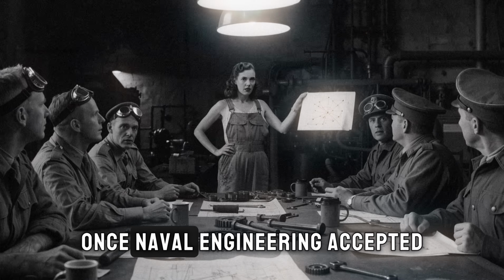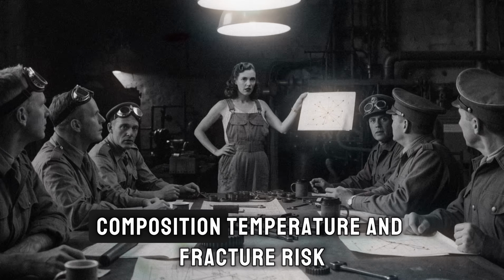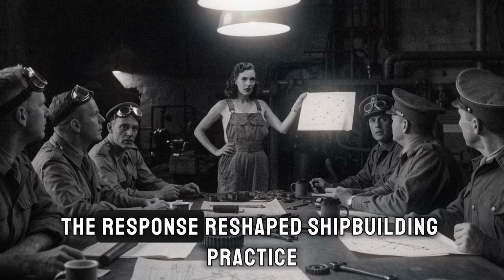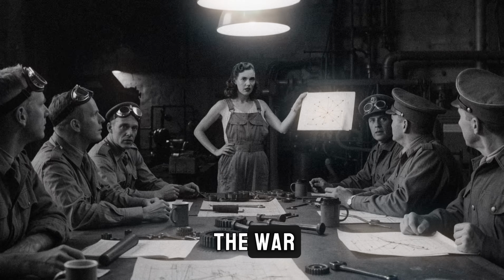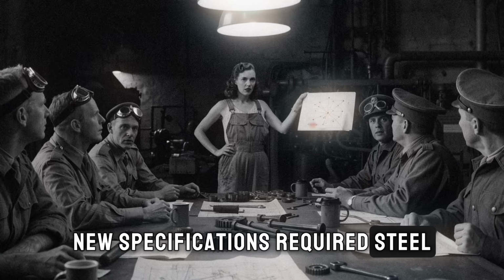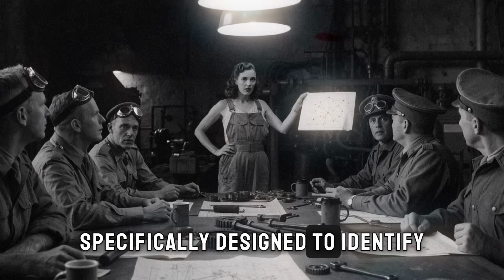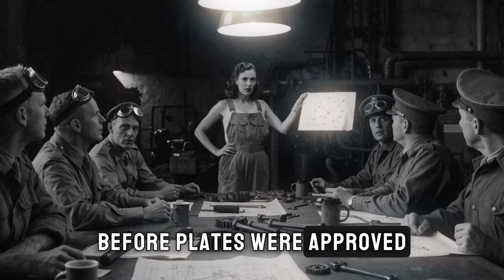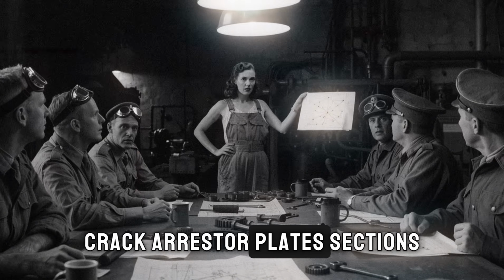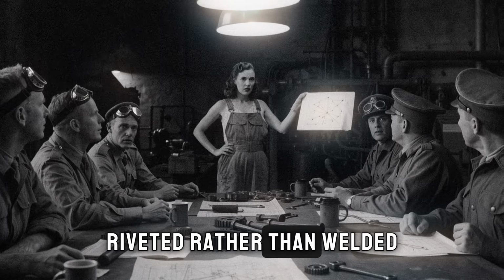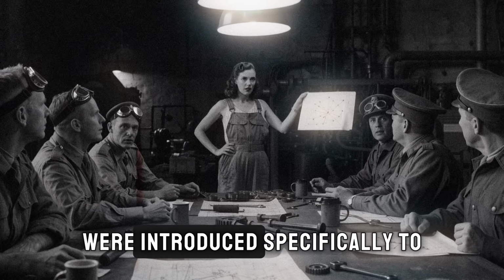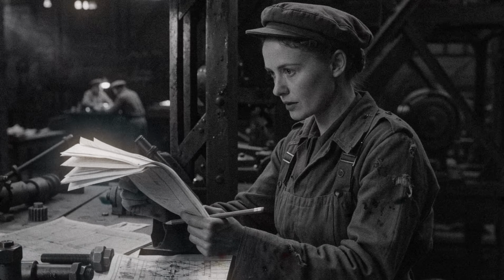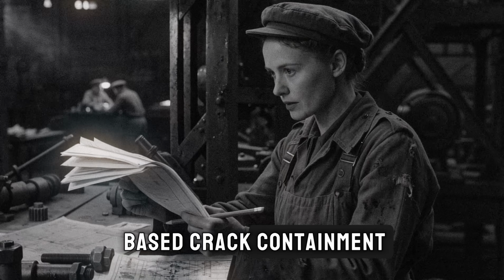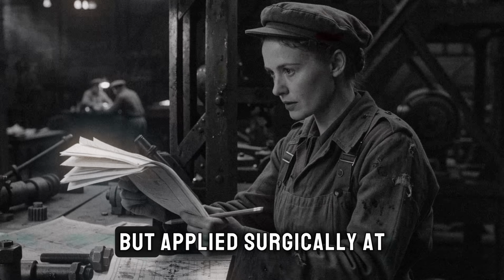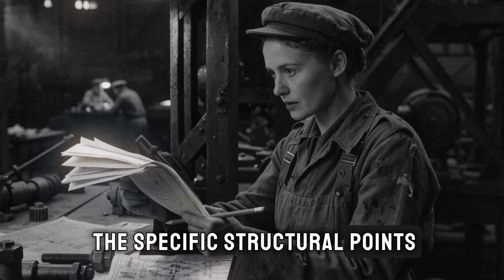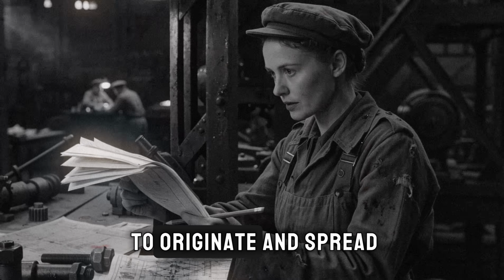Once naval engineering accepted the connection between steel composition, temperature, and fracture risk, the response reshaped shipbuilding practice for the remainder of the war. New specifications required steel testing at low temperatures specifically designed to identify brittle behavior before plates were approved for hull construction. Crack arrestor plates, sections of more ductile steel, riveted rather than welded into strategic points along the hull, were introduced specifically to interrupt fracture propagation, essentially reintroducing the joint-based crack containment that riveted ships had possessed naturally, but applied surgically at the specific structural points where analysis showed fractures were most likely to originate and spread.